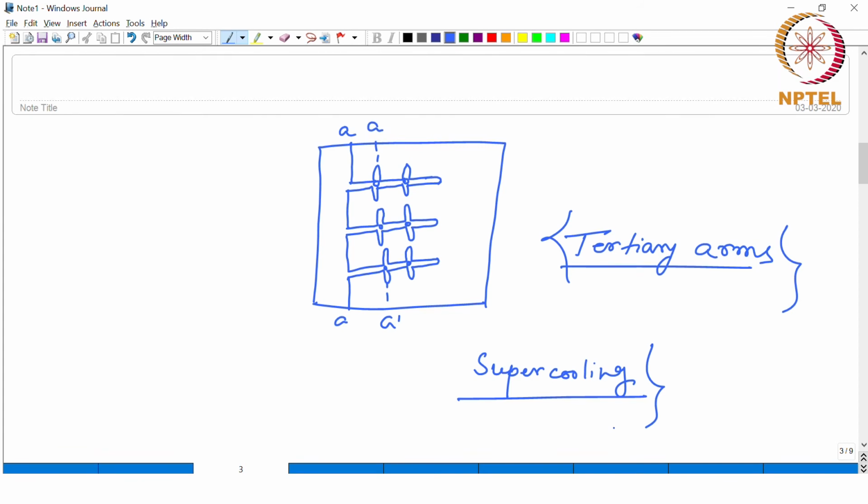So, therefore, it also means that for the dendritic growth to continue, a sufficient amount of supercooling is required in the liquid. Okay. So, in absence of large supercooling, it is expected not to have complete dendritic growth, right, because the driving force behind the growth of these cells or the dendrite itself is supercooling, right.